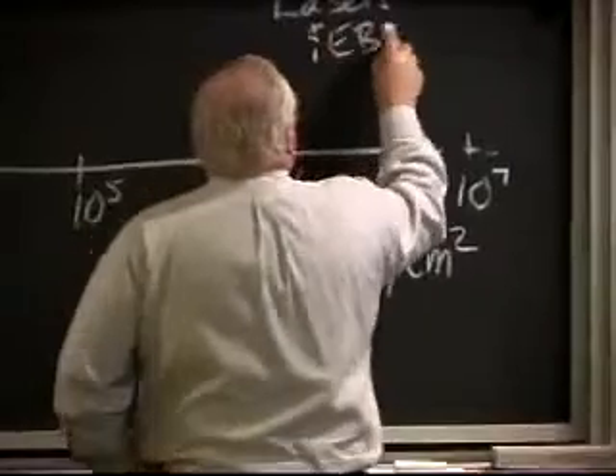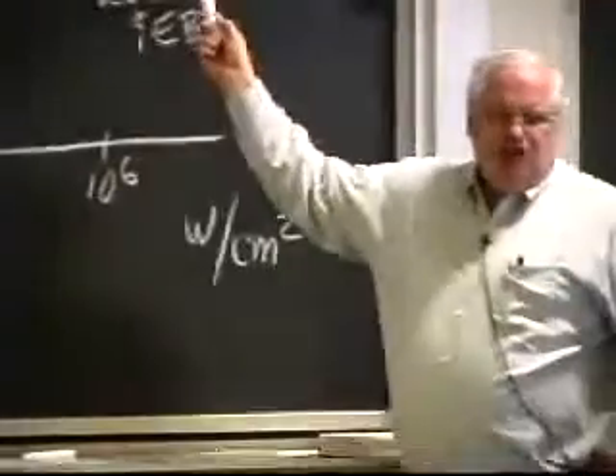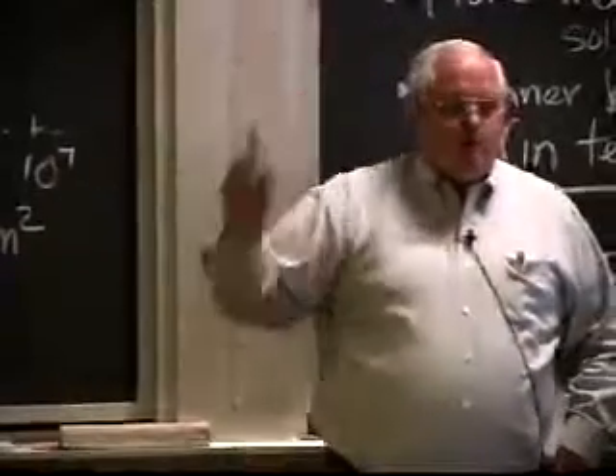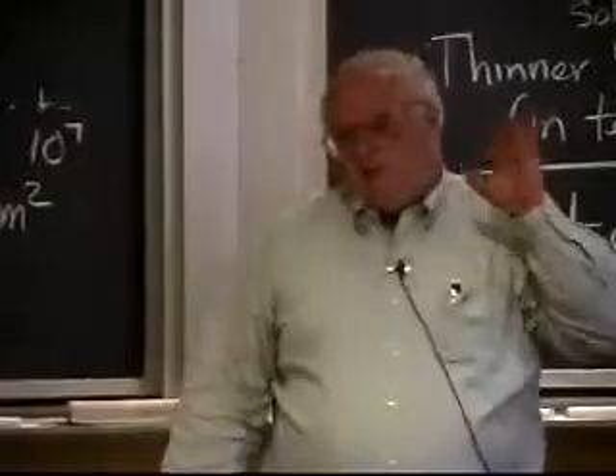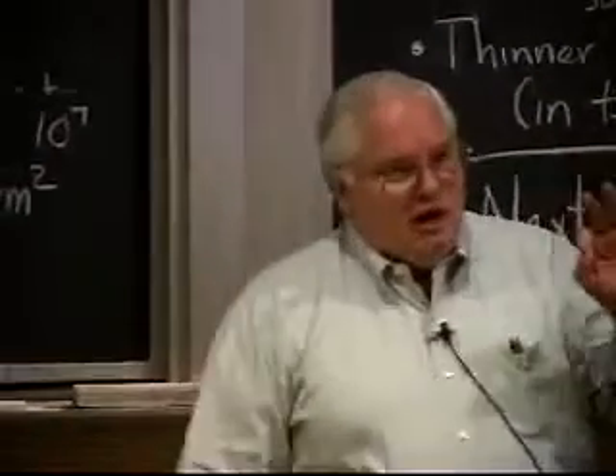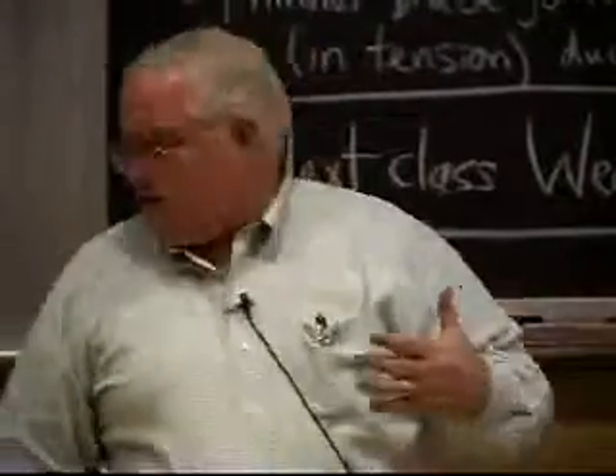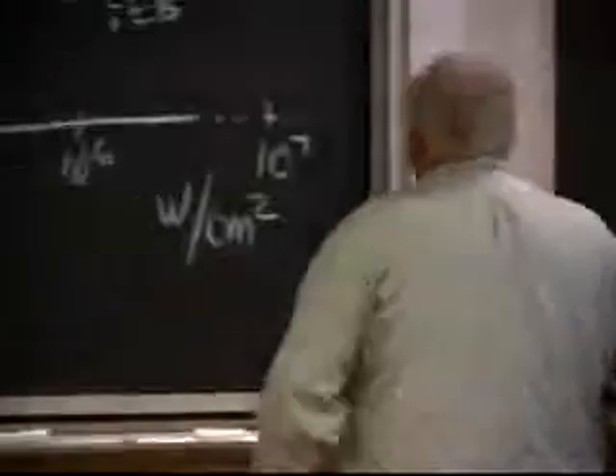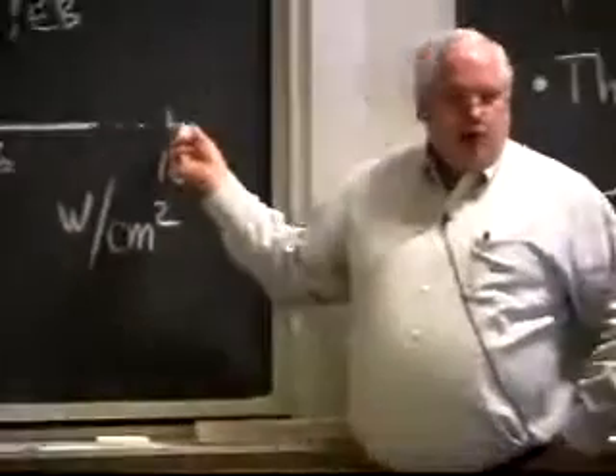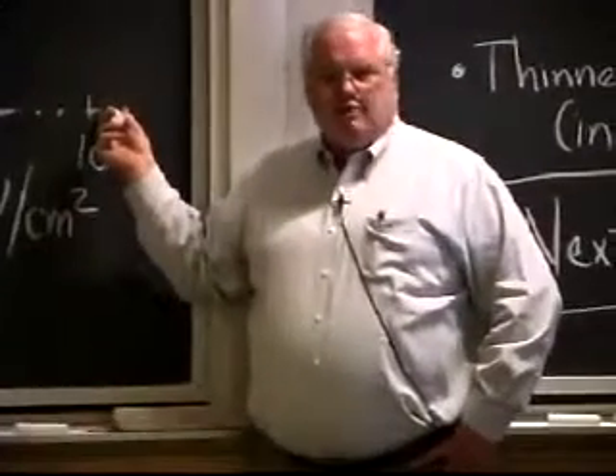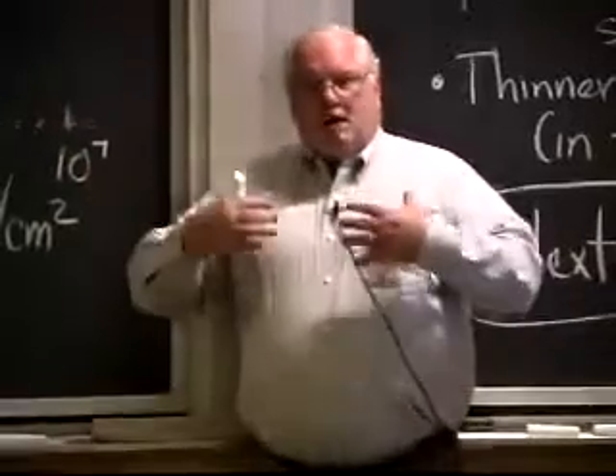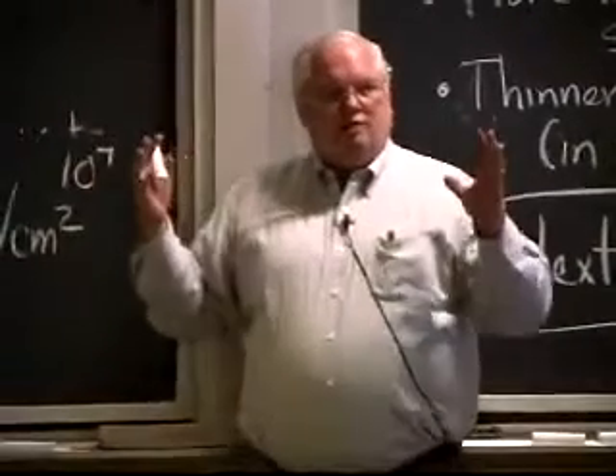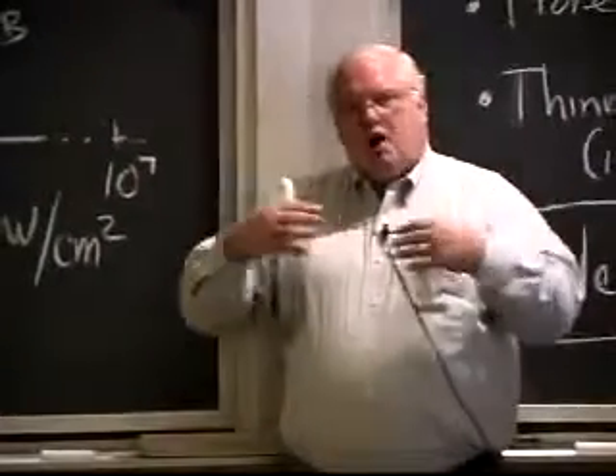In fact, in special pulse lasers, you can get 10 to the 10th or 10 to the 12th watts per square centimeter. Now, just for a few nanoseconds, but nonetheless, you can get very high heat intensities. And in fact, that's what they do with laser weapons or particle beam weapons. They're trying to hit them with something like 10 to the 7th watts per square centimeter. And you essentially ablate the material.